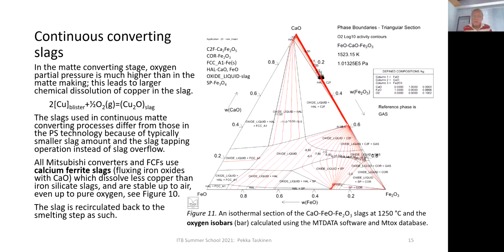They are dissolving slightly less copper in similar conditions compared to iron silicate slags, and that together with this higher stability, more wide range of the molten slag in terms of oxygen pressure, are important features, and that is why calcium ferrite slags are used in all continuous copper converting facilities.